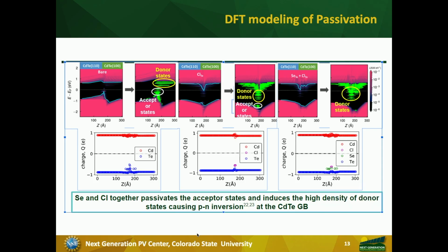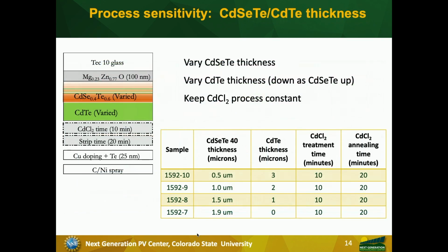Now, I also want to mention that we do modeling of the quantum mechanics of what goes on at the interface. Here is an interface between 2 grains. And if you only passivate it with chlorine, you get donor states and acceptor states that are not as good. And if you do only selenium, they don't passivate that well. But if you combine chlorine and selenium, they make donor states, which is a good passivation. And we are some of the early applicants of density functional theory modeling to the cadmium telluride solar structure.